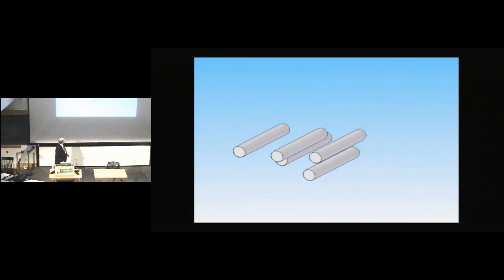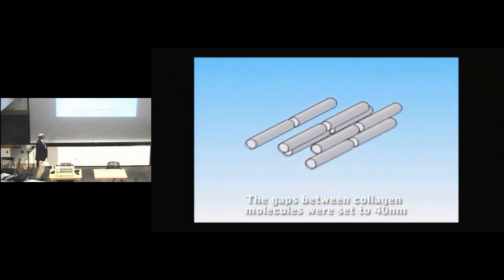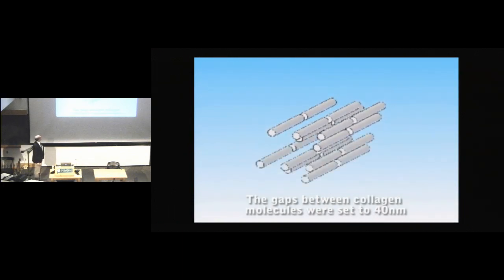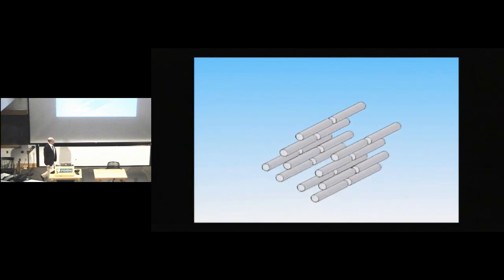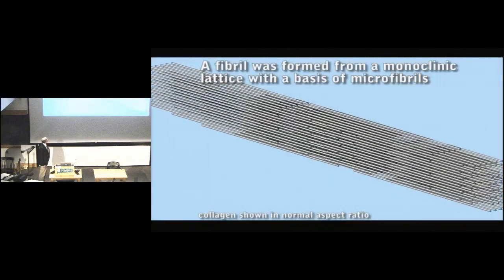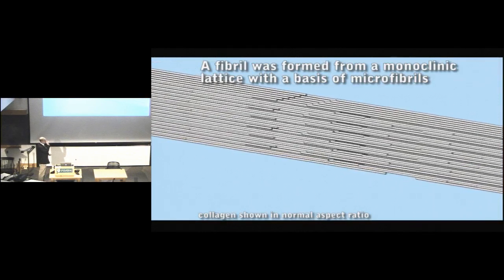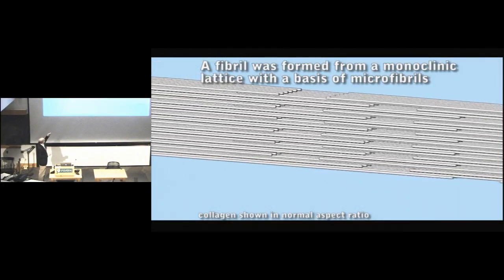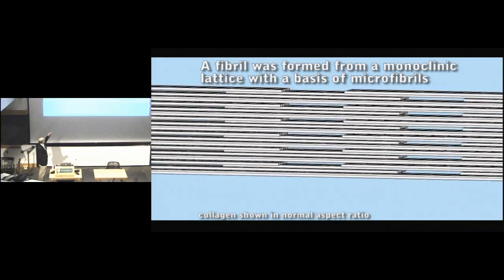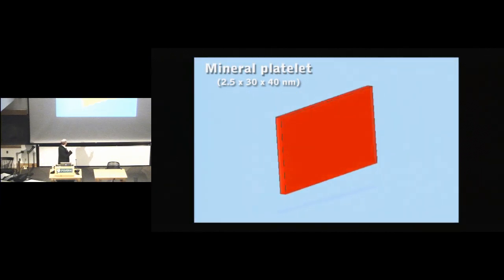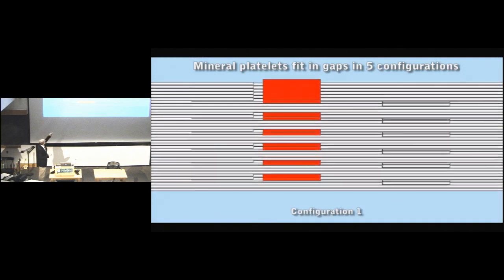And then the way these stack together is in a nominally orthorhombic Bravais lattice, with a very mild twist to it that we're not accounting for. And then when we take these out and stretch these back out, we end up with a structure that's very dense, that has pockets in it that can accommodate mineral only in a few directions. And the mineral platelets are these dimensions, so about 2 by 30 by 40 nanometers. And you can see there are only a few orientations in which they can fit in.